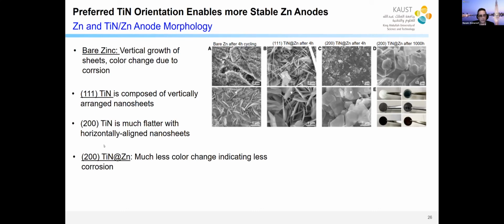And also, this results, if you look at the sample after the cycling test, the initially pure zinc becomes corroded. This becomes dark. And this black, titanium nitride is a conductor, so it's a dark color. So this black is the titanium nitride. After cycling, it also is corroded. And then the 200 titanium nitride remains actually intact after cycling.